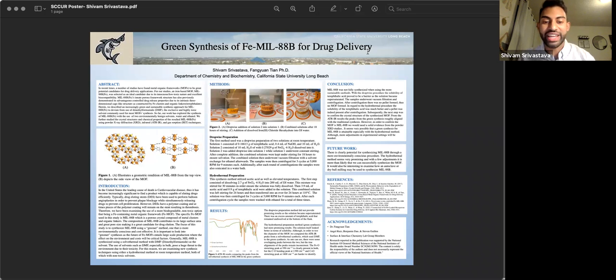From this pellet, we ran IR in order to confirm the character of the MOF we produced. And the results were promising, except they did not align completely with the solvothermal method that we usually use to synthesize MIL-88B. As one can tell, the peaks look very similar in their alignment, but they're not as exact as they should be. So it promises to be a good method using the hydrothermal preparation, but more studies and adjustments still need to be made to confirm it.